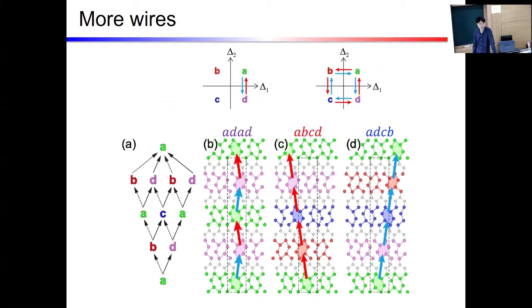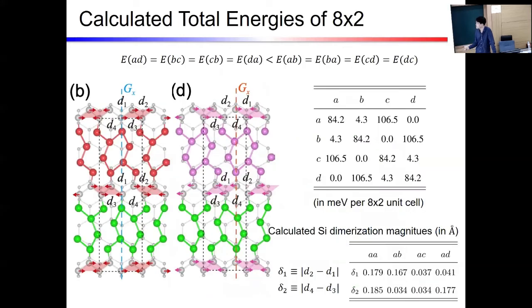What was the reason you cannot go from A to C? Because of high energy. Yeah, AC is the highest energy. That is the energetics. Actually, the experiment also confirmed this a long time ago. The shape is always an alternating return, which means they don't form a chiral pattern. A and C would actually be a chiral pattern, they just translate, right? So the system prefers chiral patterns only.